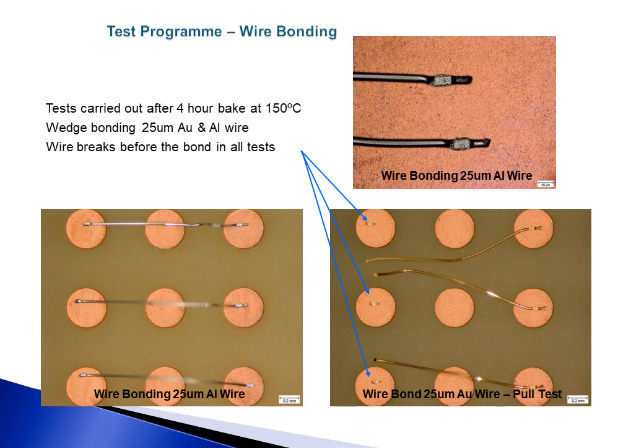My next challenge was, well, can you wire bond through it? So I went off to a company that specialised in wire bonding and worked with them on a couple of visits. And we were able to achieve very good wedge bonding results for both aluminium and gold wire. And we got to a point where the wire was breaking before the bond in all the tests. I tried ball bonding, but that was a no-go. I suspect because of the coefficient of friction of the coating.